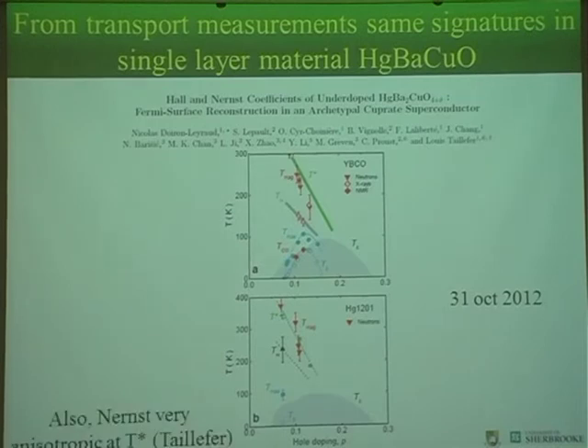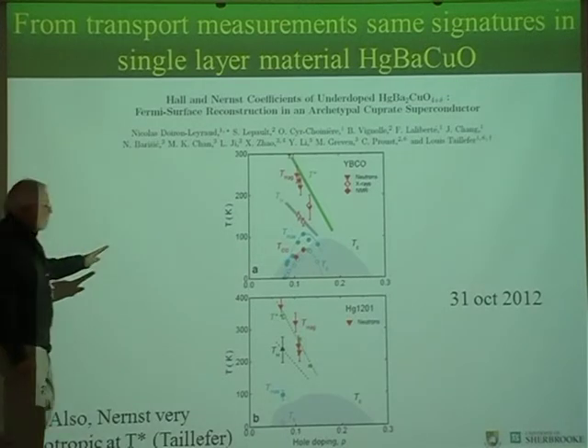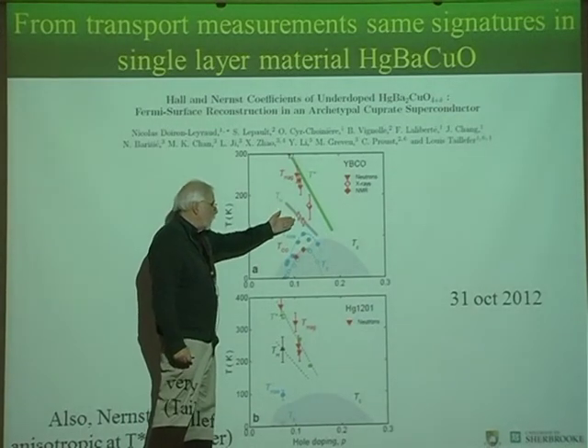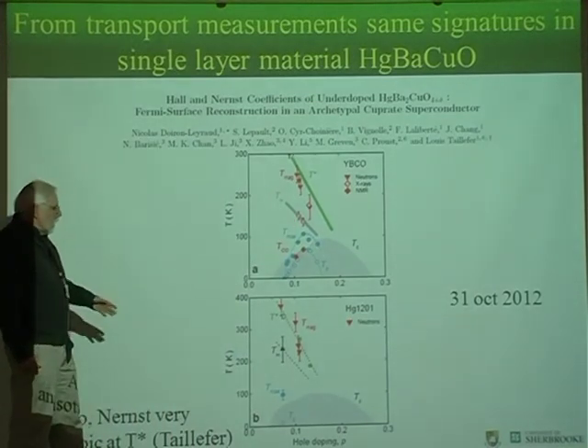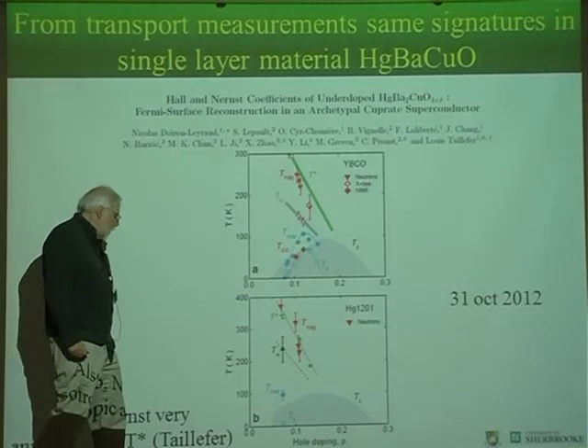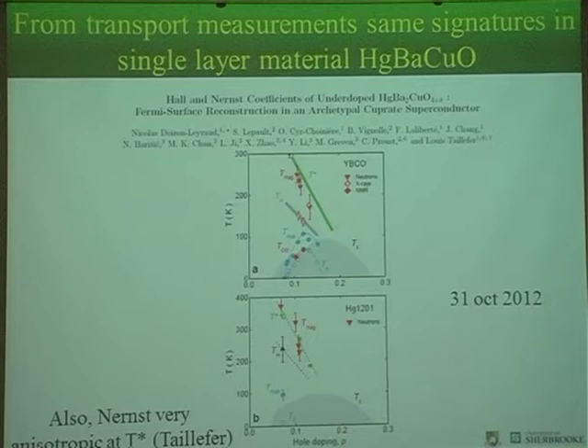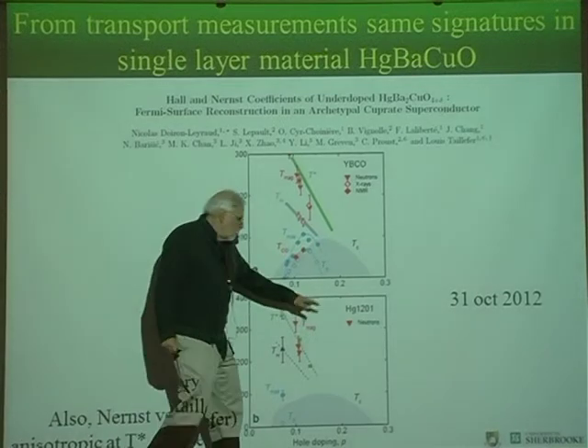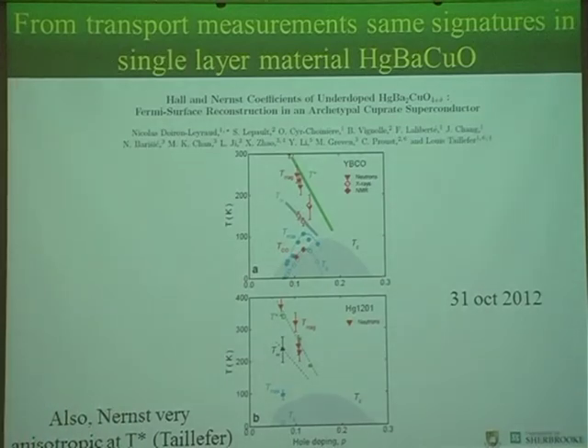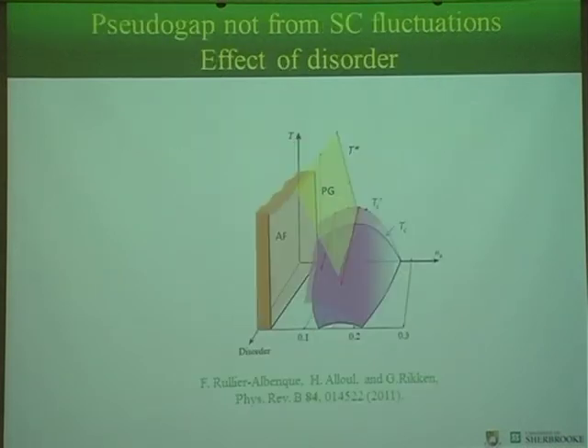Now, I won't go through this, just to say one thing. It's just that there are signatures of this charge density wave in transport measurements. They were first suggested, in fact, by transport measurements. These are these experiments of Taillefer I mentioned earlier. And these same signatures are seen in this one-layer compound that's mercury 1201, because the yttrium barium copper oxide has 2 layers, 2 copper oxygen layers per unit cell. And then people are always worried that this is sort of an artifact of this bilayer thing. But even in single layer compound, you can see these effects.